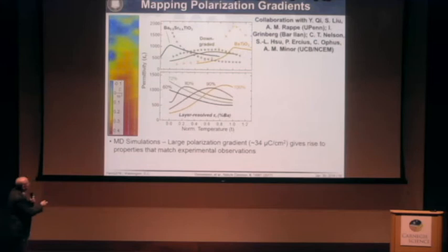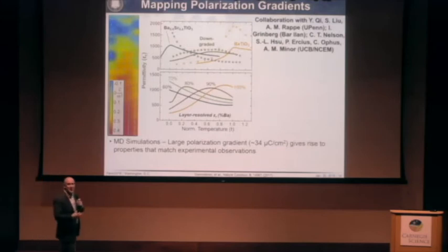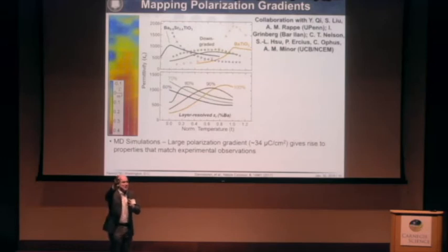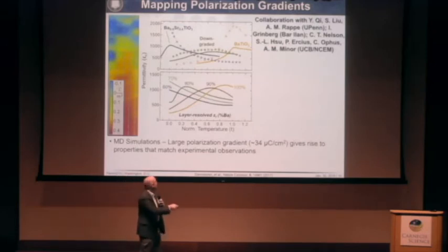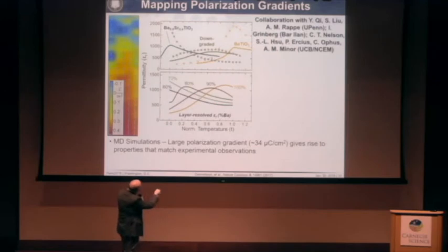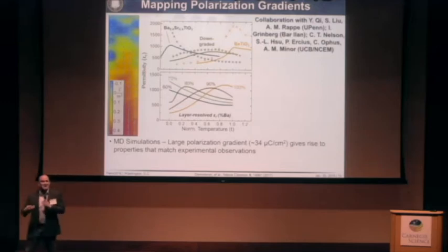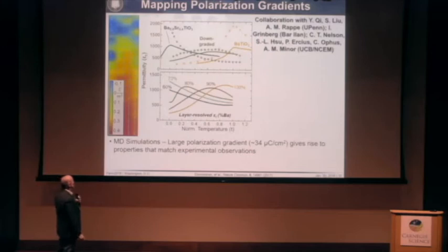And the way we've figured this out is by basically thinking of a bunch of individual layers of the different compositions inside of here. If I go through at any one point, there's some layer of a specific composition which is going through its transition temperature, and they're all just shifted from each other. And so as we go across this regime, we're adding the collective effects of all of these different compositional layers to give rise to this broad temperature response inside of these systems.